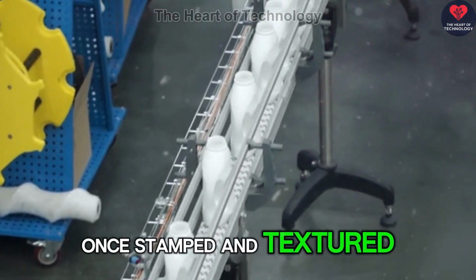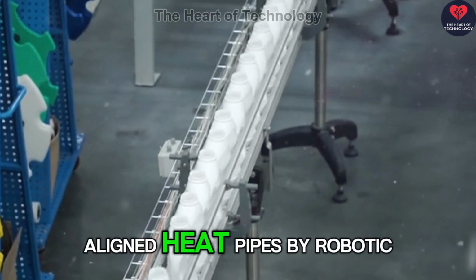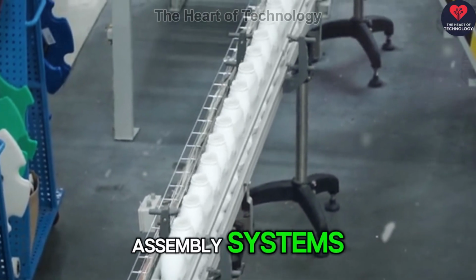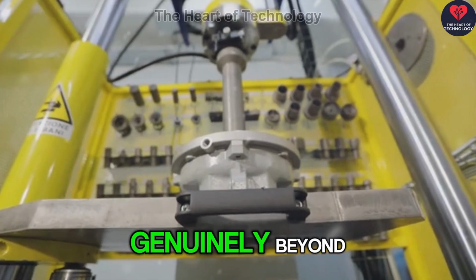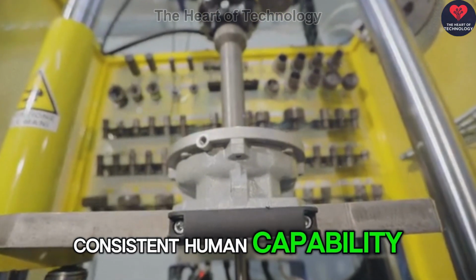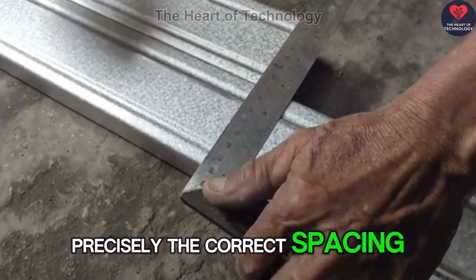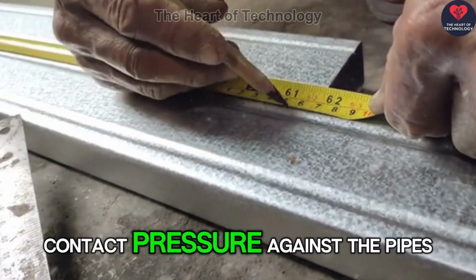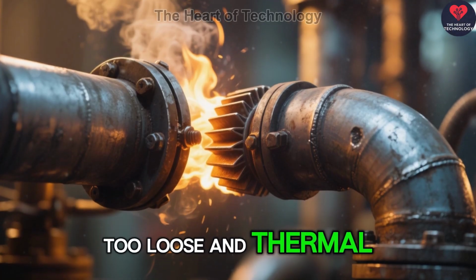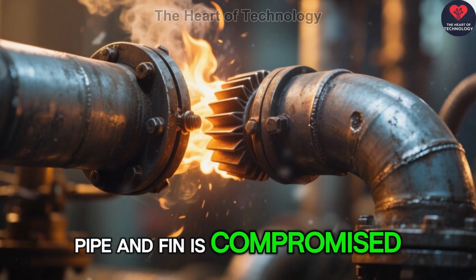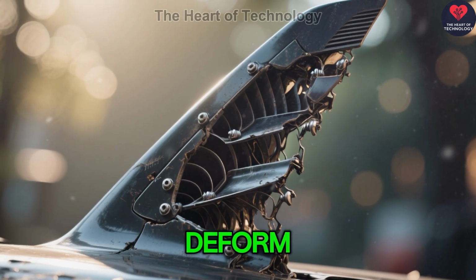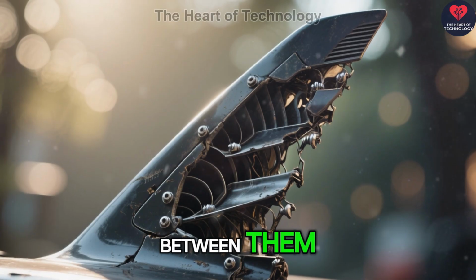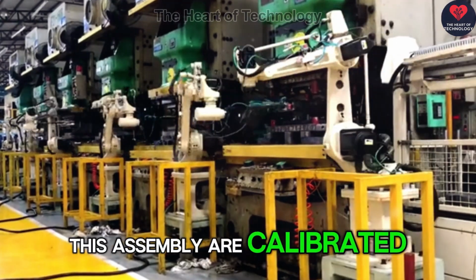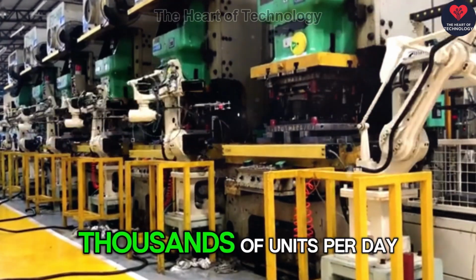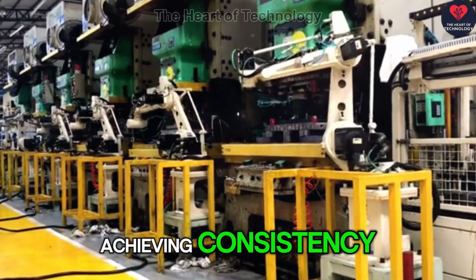Once stamped and textured, the fins are threaded onto arrays of aligned heat pipes by robotic assembly systems. The tolerances required for this step are genuinely beyond consistent human capability. Each fin must sit at precisely the correct spacing, with precisely the correct contact pressure against the pipes. Too loose and thermal transfer between pipe and fin is compromised. Too tight and the fins deform, disrupting the airflow channels between them. The robots that perform this assembly are calibrated to maintain these tolerances across thousands of units per day, achieving consistency that no human-operated line could match at scale.